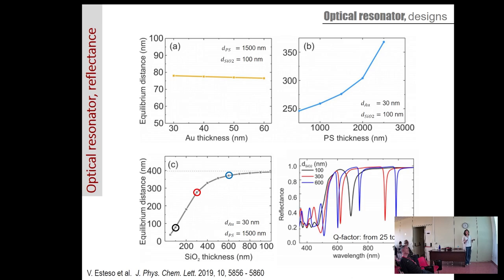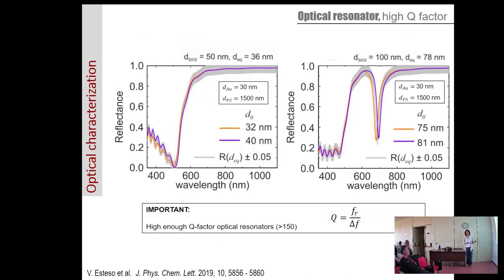How does the reflectance spectra of this system look? They look like something that we wanted to have, actually. This is the reflectance of silica films of 100, 300, and 600 nanometers. They have very low Q factors, but still enough to be accurate in the measurement of this cavity size, as I'm going to show you now.